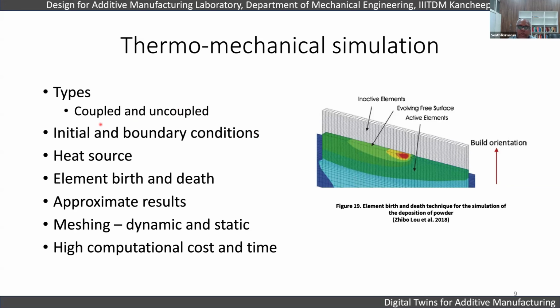In a coupled thermomechanical problem, you're going to basically change every element after taking the results from the previous simulation. In uncoupled, you first solve the thermal and then bring it to the mechanical simulation, and then update your next iteration for the thermal simulation, right? So here we have the initial and boundary conditions. The initial conditions are the initial temperature of the powder. The boundary conditions are typically what is happening in the convection in the surroundings and things like that. So then we have to model the heat source.